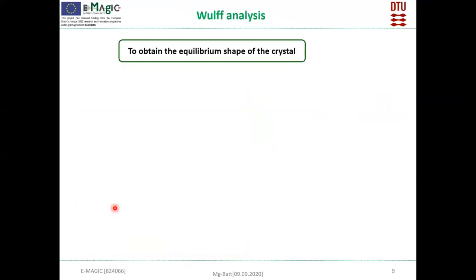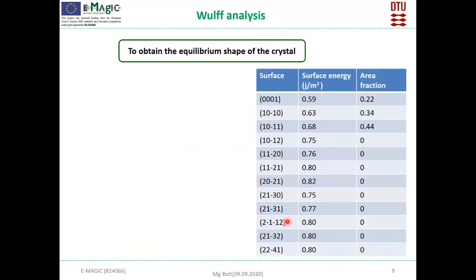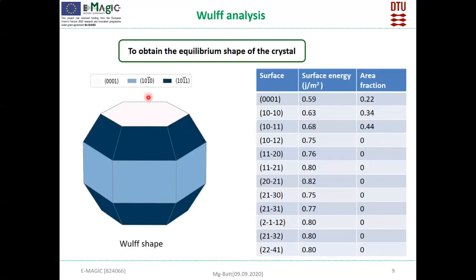And for that, first we analyzed which surfaces are present in magnesium at equilibrium condition. We used the Wulff analysis to obtain the equilibrium shape of the crystal. We considered almost 12 surfaces in magnesium and calculated their surface energy, and we constructed the Wulff plot. From the Wulff plot, it is clear that only 3 surfaces will be present in magnesium at equilibrium conditions: the 0001, 10-10 and 10-11 surfaces. And you can see the area fraction of each surface here. Then we further studied these surfaces, whether the dopant prefers to go to the surface or the bulk.